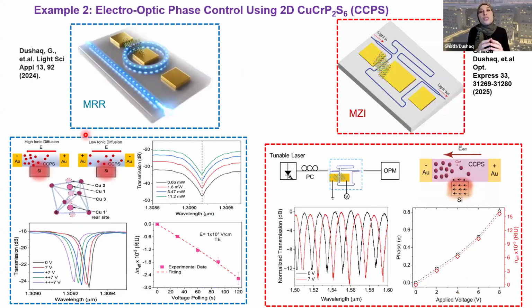The second application, which is actually now viral, is phase shifting. It's a fundamental element for linear weights in a photonic neural network. Also, if you want to add nonlinearity by going to the nonlinear regime of this ferroelectric material, these are the hard core of the matrix multiplication in AI, where you want to electro-optically tune this material precisely in phase without losing the signal. And this is what we've been doing here using CCPS material, which is a multiferroic material.